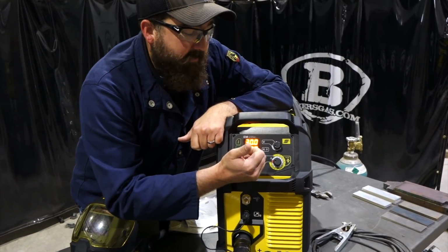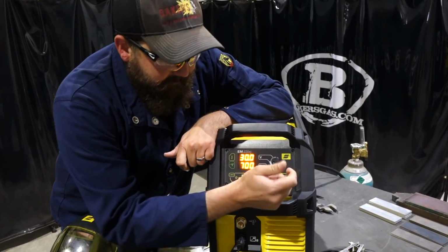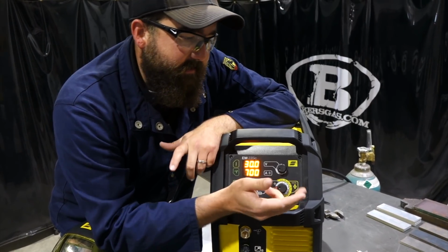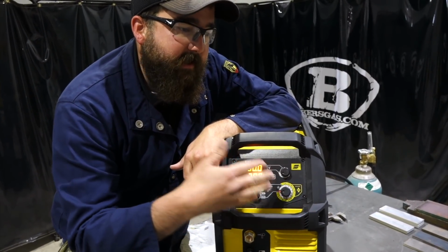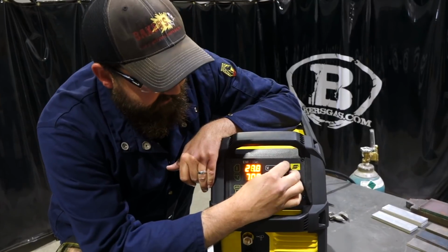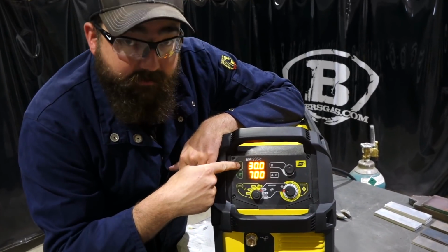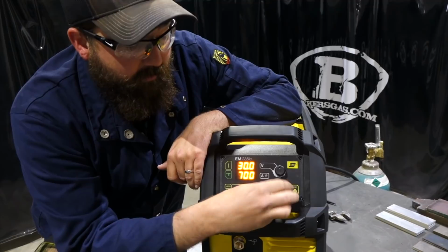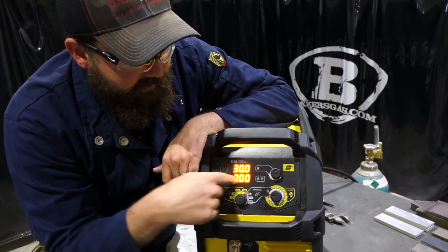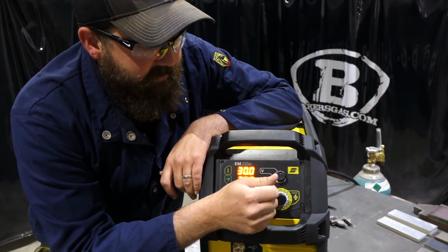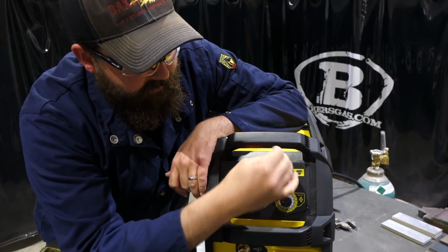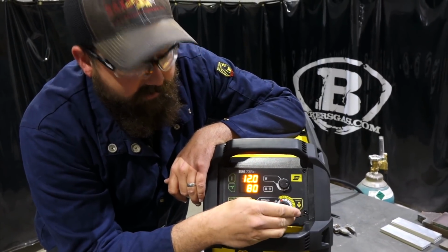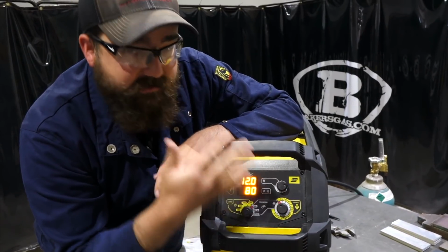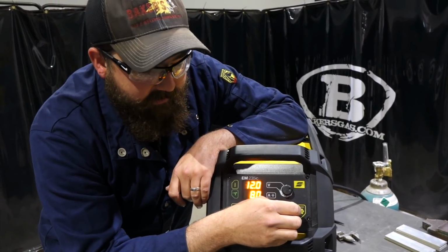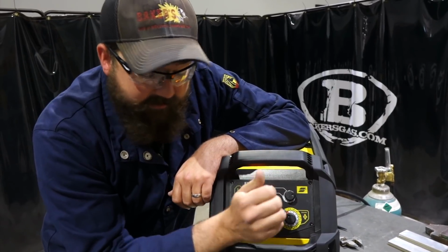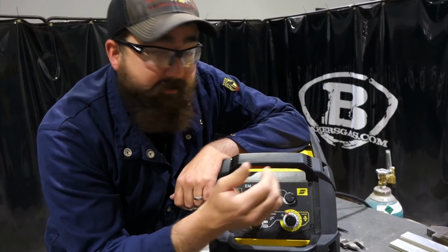We talked a little bit about duty cycle. On 230 volt, duty cycle on this machine is 26 volts at 240 amps, and that's at 40%. But as you can see, we can max this machine out to 30 volts, and then on our wire feed speed selector here, we can go up to 700 inches a minute, which is pretty amazing. Now this machine will back down to 12 volts and 80 inches per minute on wire feed speed. So it's got a wide range of versatility in it. It's pretty sweet.